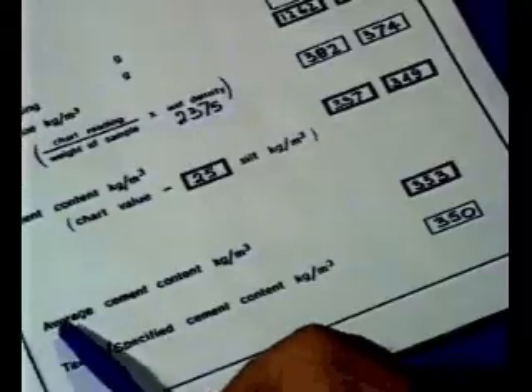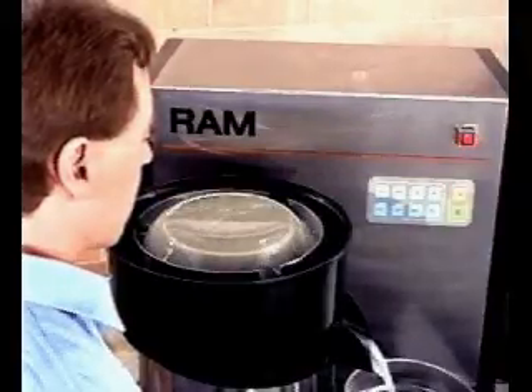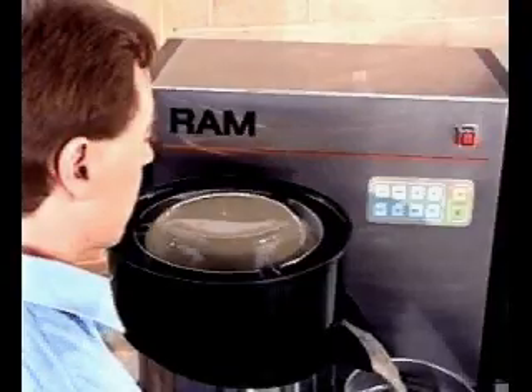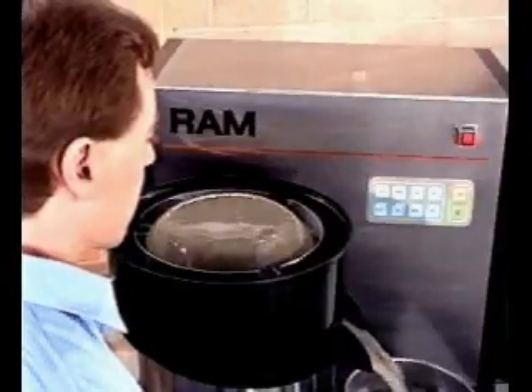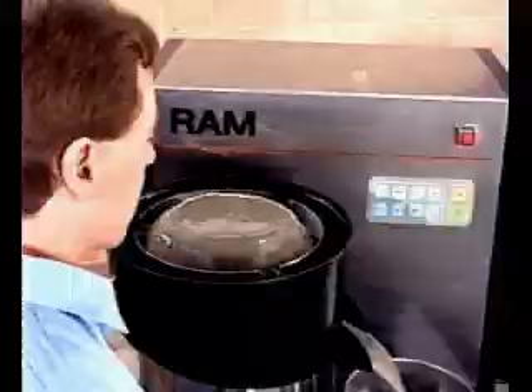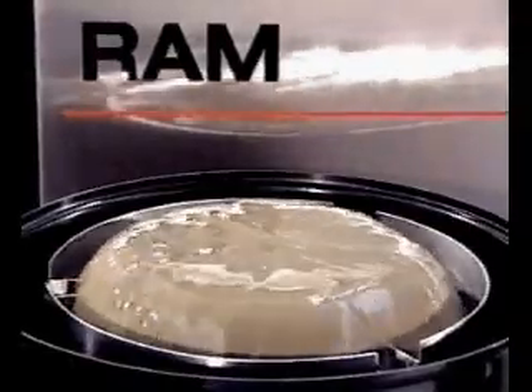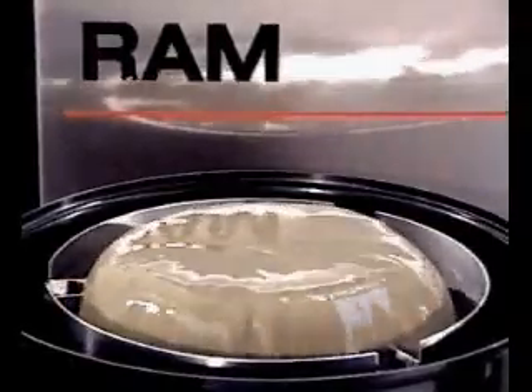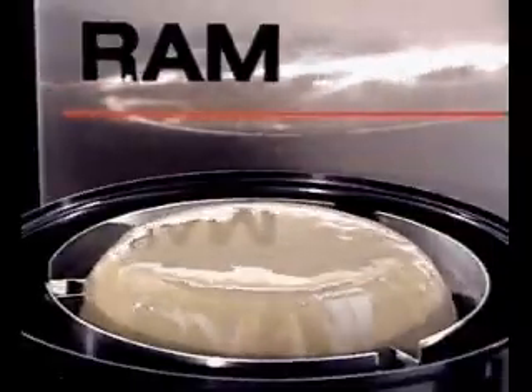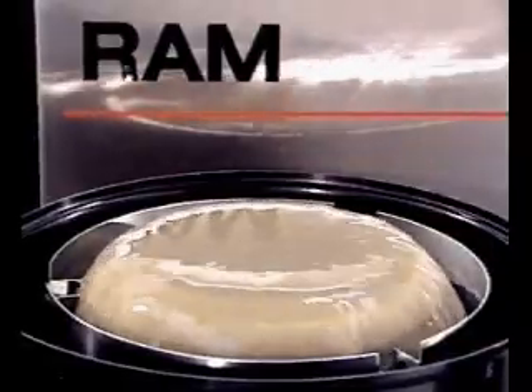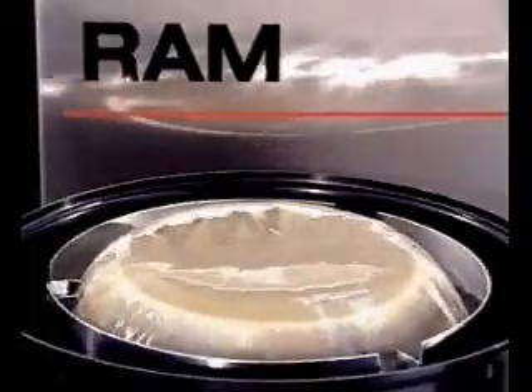In practice, the overall accuracy, including errors due to sampling and any correction for silt content, will normally be within plus or minus 10 kilograms of cement per cubic meter. The whole process takes less than 10 minutes and is possible in the short time available between mixing and placing. RAM provides a practical method of checking cement content to ensure that the concrete meets the requirements for strength, durability, and resistance to chemical attack.